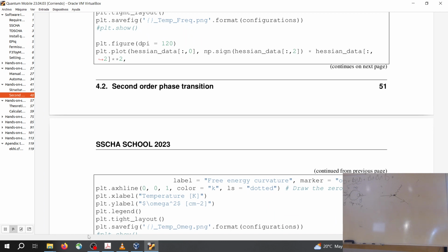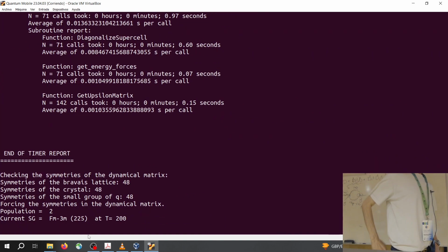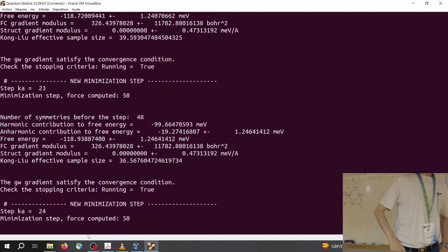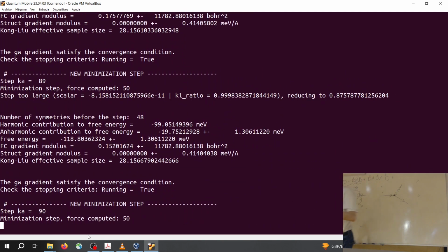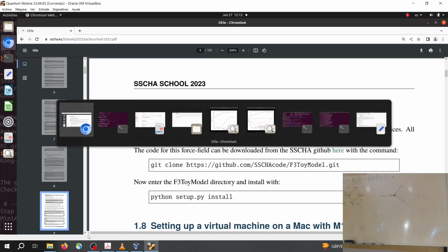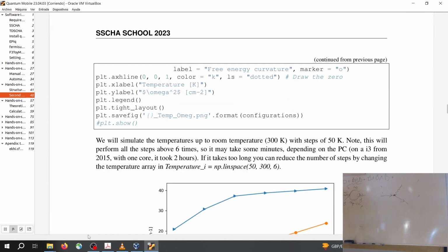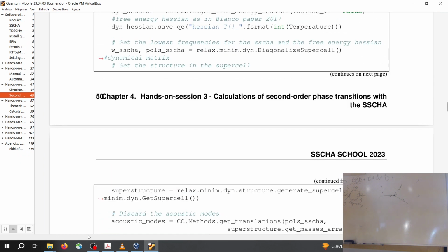It's not because of the loop. If you remember from Rafael's lecture, he didn't give the explicit equation when he was calculating the average of the third order force constant; we can check the papers. This implies calculating averages of displacement and force. And for the SSCHA minimization, you need displacement and force. So statistically, it's more difficult. It makes sense that for the Hessian you need more configurations, because it's a more complex, higher order variable. That's why you normally need more configurations to converge the Hessian. You should check if the number of configurations that you choose is enough, and if that's enough, then you can increase as much as you want.